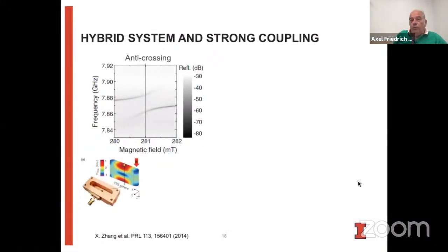In order then to faithfully transmit information between a magnetic excitation and a microwave photon, you want to be in what's known as the strong coupling regime. And this is here shown by an example from work from Zixiao Zhang, who placed an yttrium iron garnet sphere into a three-dimensional copper microwave cavity. And so what you see here is a plot of the resonance measured inside this cavity, the resonance frequency as a function of the magnetic field.